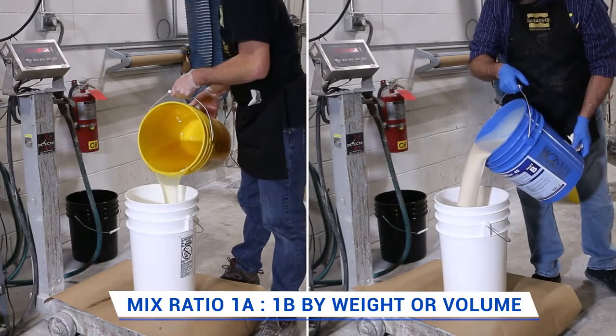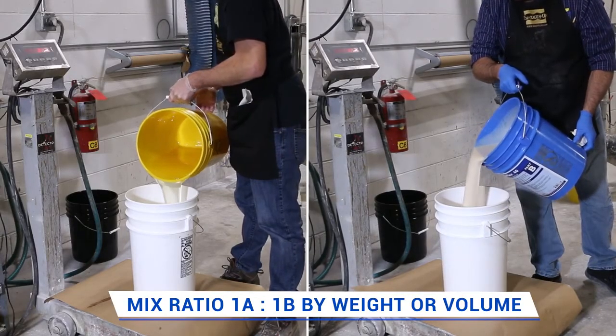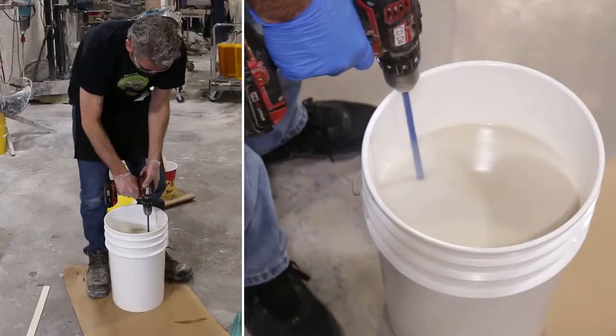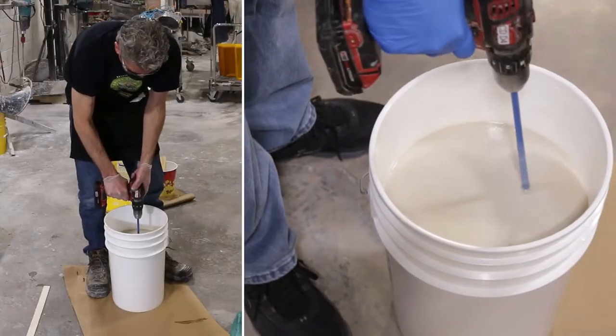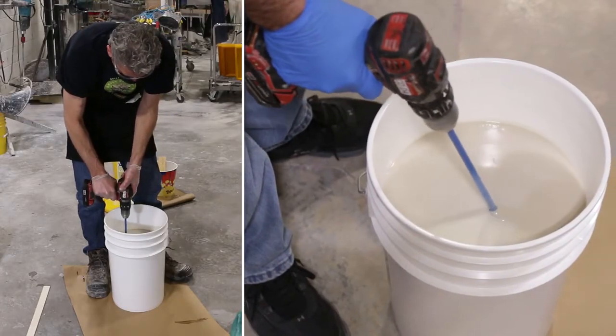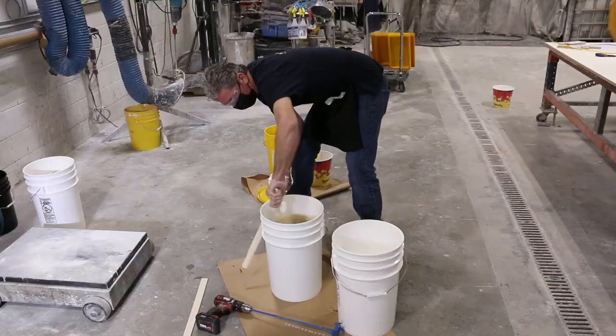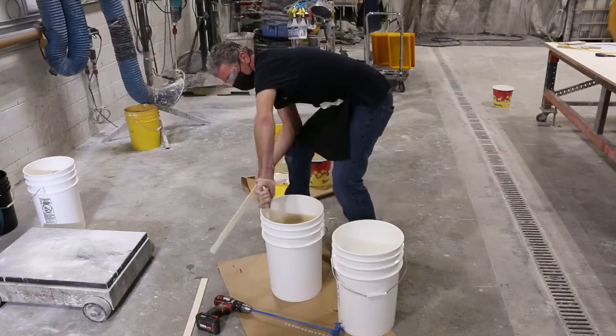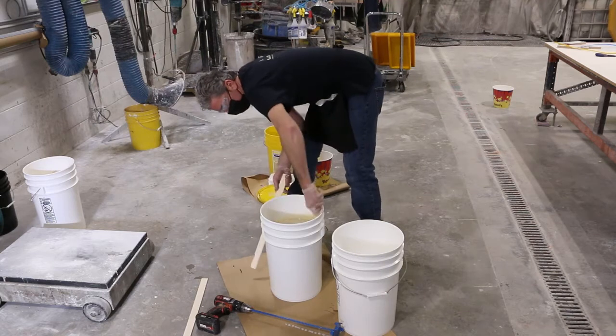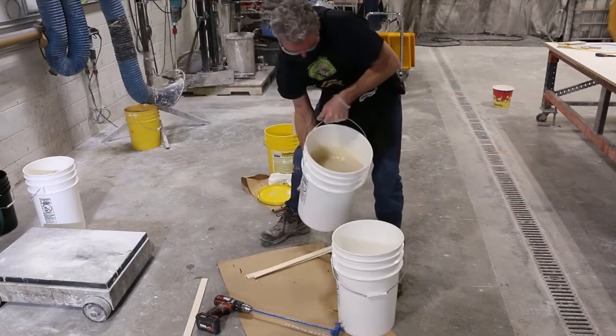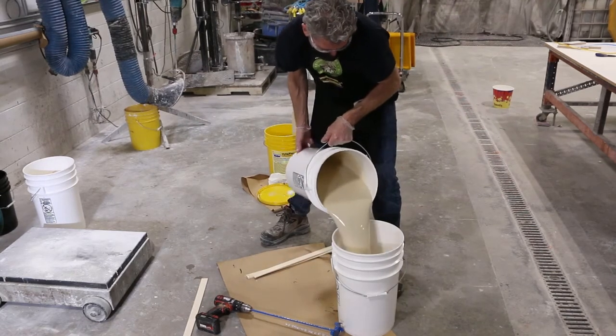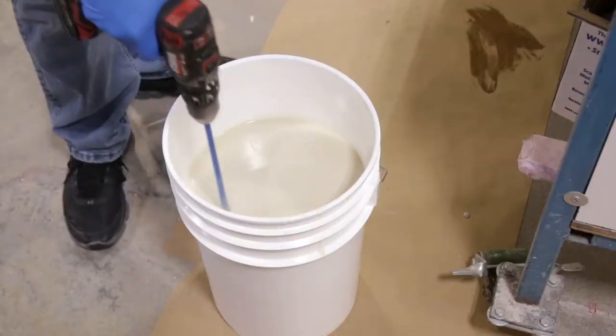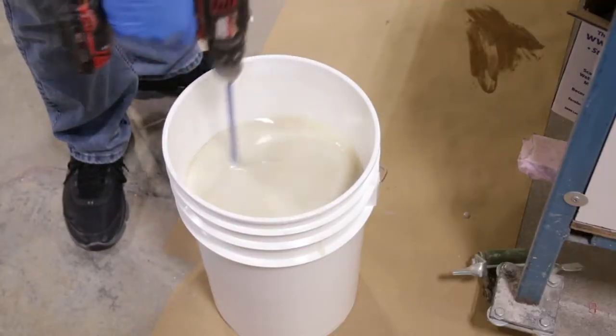Dispense equal parts of A and B, 1:1 ratio by weight or volume. Combine both parts into a clean mixing container and mix well using a variable speed drill with the turbine mixer. Scrape the sides and bottom of the container with a mixing stick to make sure to incorporate all the material. Transfer this mixture into another clean mixing container and mix again to ensure a thorough mix.